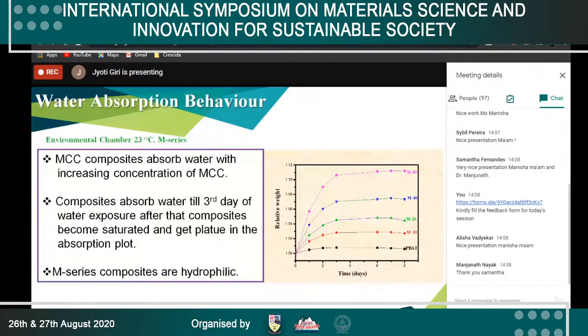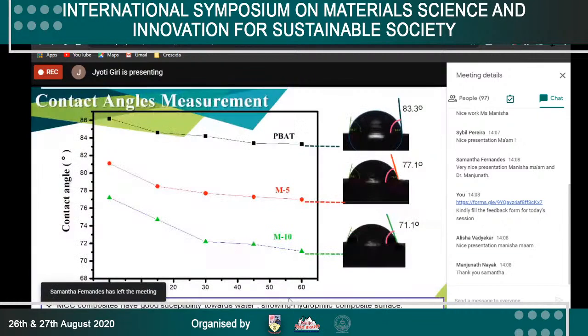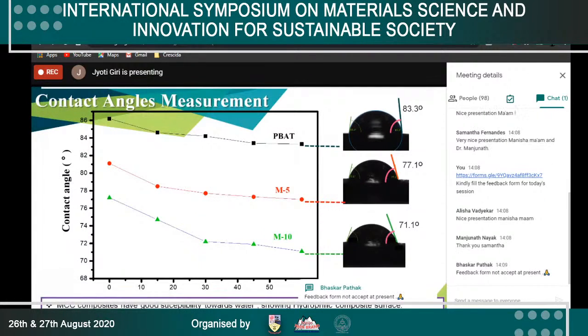studied by the water absorption, and here in this plot we can see the water absorption behavior is increasing with the increase of the MCC in the composites. That is, hydrophilicity increases with the increase of MCC in the composites. Likewise, the contact angle of the composites was measured, where the contact angle value is decreasing with the increase of microcrystalline cellulose in the composites, and at the same time, with the increase of the interaction time, the contact angle value is further decreasing, which indicates the hydrophilic nature of the composites with the increase of MCC.